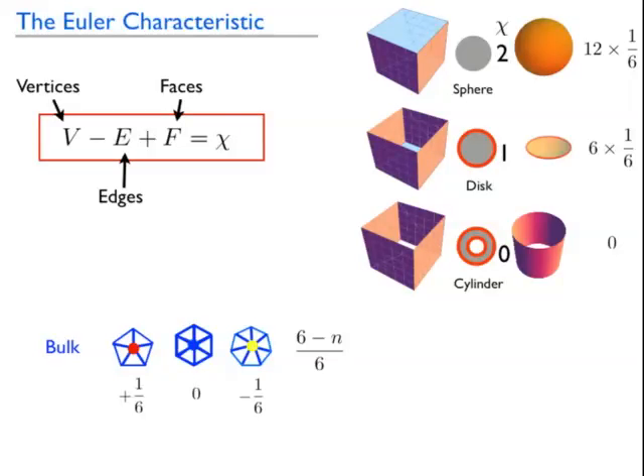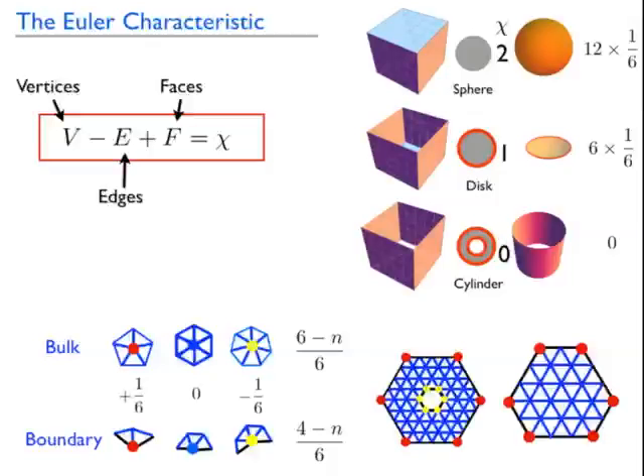But if now I don't have just the surface, but I have an edge, I have to worry about what happens on an edge. And the answer is, if I'm on an edge, if I'm on a boundary, if I have 4 neighbors, it counts as 0. If I have 3, it counts as a sixth. And if I have 5, it counts as minus 1/6.